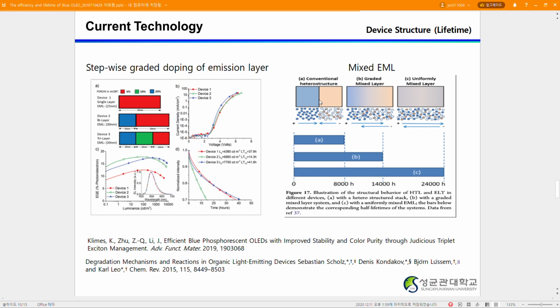This slide shows the device structure for lifetime in blue devices. This slide shows mixed host structure and graded doping of emission layer. The most effective way of adjusting the emission zone is to mix the hole type and electron type host material together. Although the bipolar host and the thermally activated delayed fluorescence type host can control the emission zone, a mixed host is even better than a bipolar host because various combinations can be easily accessed.